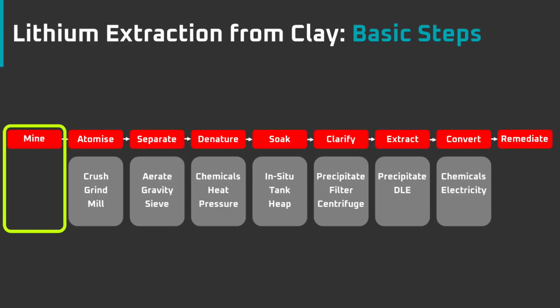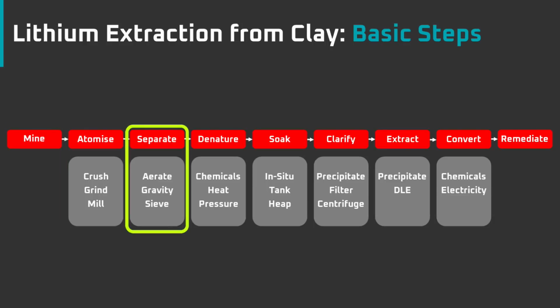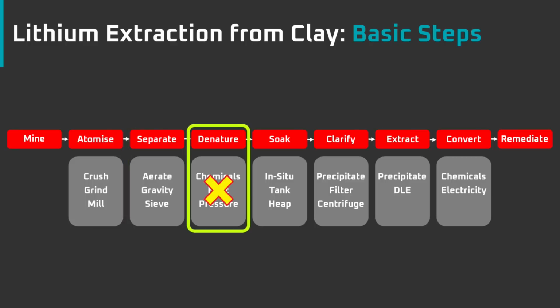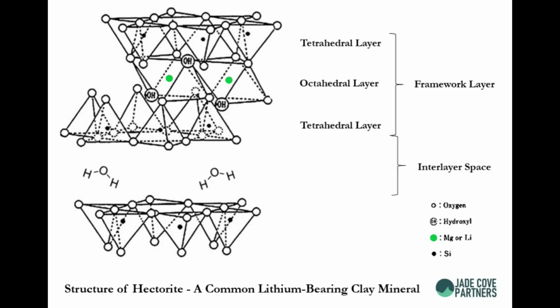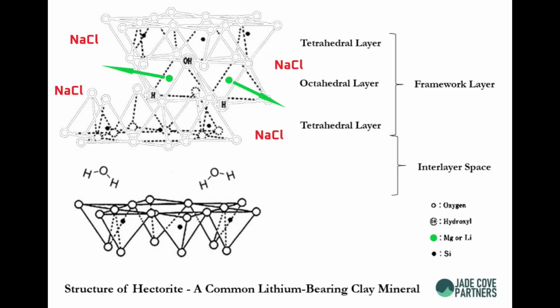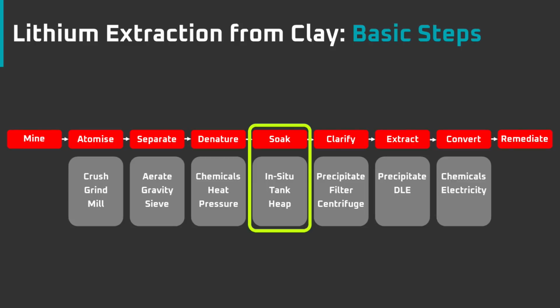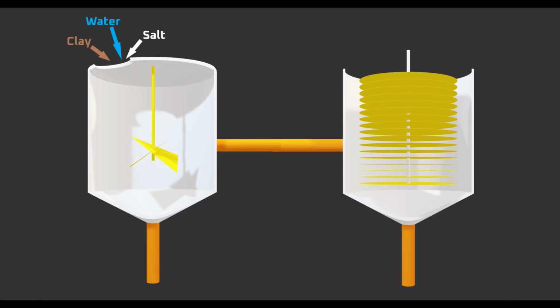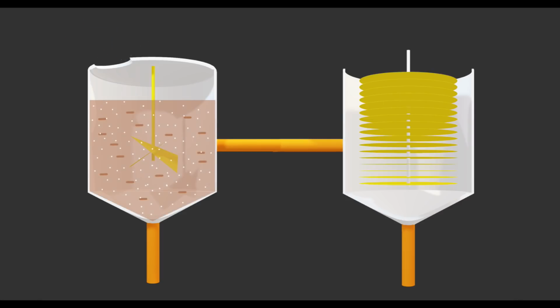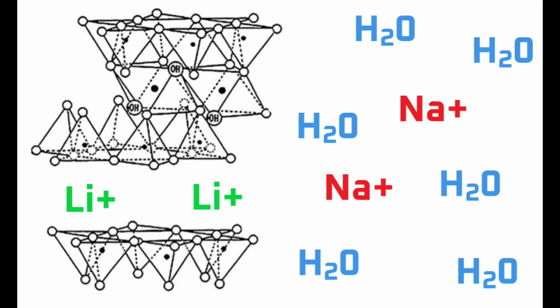Tesla starts by mining, atomizing, and then separating the material with a process that's optimized for their lithium clay. The denaturing step would be skipped because the crystal structure wouldn't need to be destroyed to release the lithium. In the soaking stage, the atomized and separated lithium clay powder would be added to a tank where it's mixed with a saltwater solution. The lithium in the interlayer has a stronger attraction to water than sodium in the table salt. This means that under the right conditions, some of the sodium from the sodium chloride might swap places with the lithium, releasing the lithium into the solution.